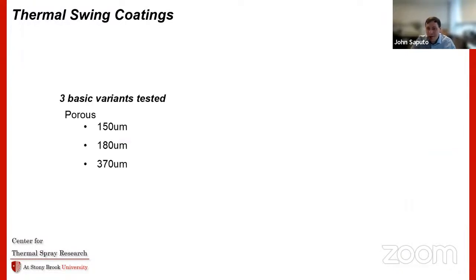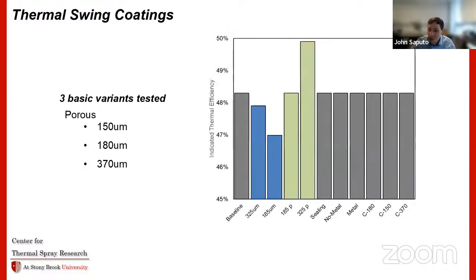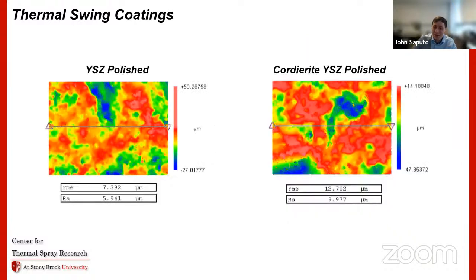But we also did 3 variants of thicknesses in this. So we did about 150, 180, and 370 microns in case that's an issue. We did see that earlier. But for all of these cases, we see absolutely no change to engine performance. So our thought with this was maybe it's the roughness. We already determined that that's interesting. So you look at the zirconia coating. I said it's about 6 microns Ra. Here I'm showing it's 5.9. On the right, this is the cordierite zirconia piston.